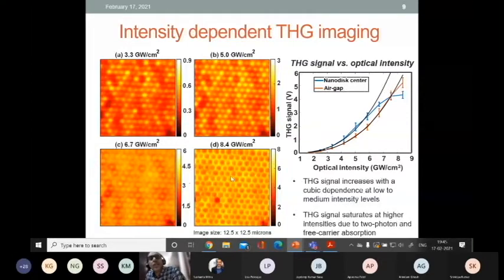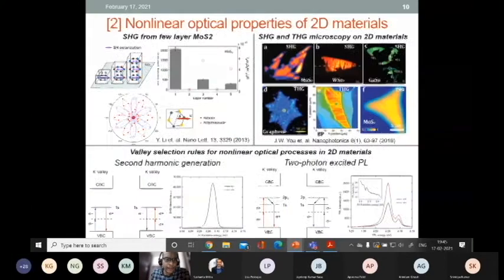So what the nonlinear microscopy system allows us to do is to really understand how these saturation behaviors get started, where they occur, and how they progress with increasing intensity. You get a real spatial map of how things happen, how saturation occurs, and so on. The aim here is to use these intensity-dependent images to better engineer our nanostructures so that the onset of saturation can be extended to higher intensities.